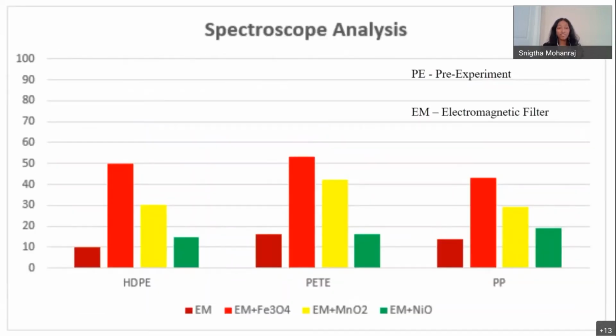So I performed a spectroscope analysis in which I actually created my own homemade spectrometer. And this spectrometer measured the intensity of transmitted light through samples. And so across all of these tests, across different forms of microplastics, it was shown that iron oxide with the electromagnetic filter was the most effective methodology to be using, but manganese dioxide and nickel oxide did further increase the efficiency of the plain electromagnetic filter, just iron oxide was able to increase it the most.